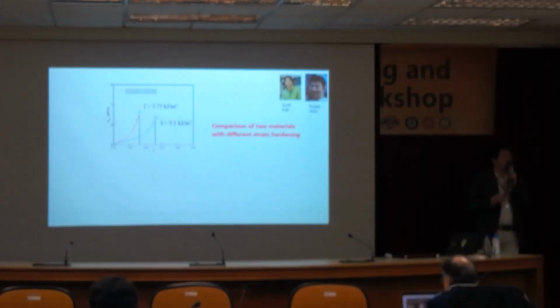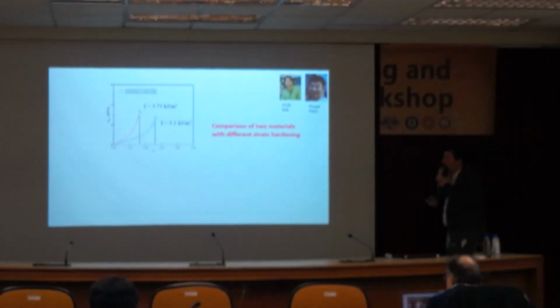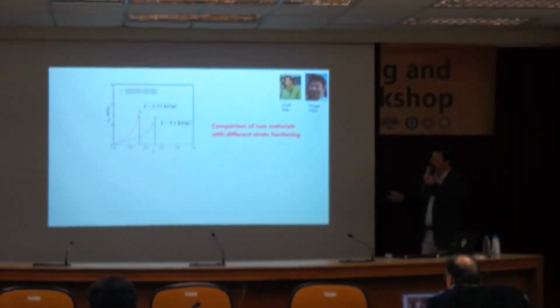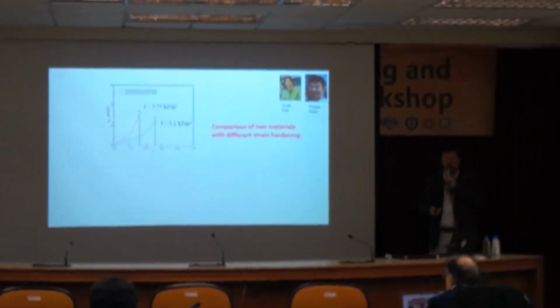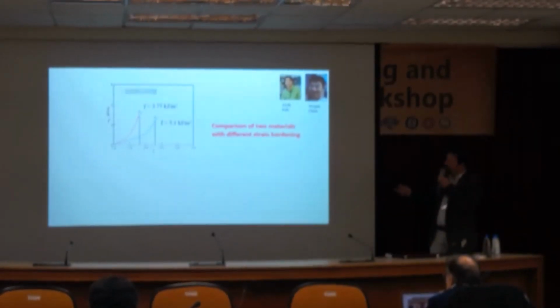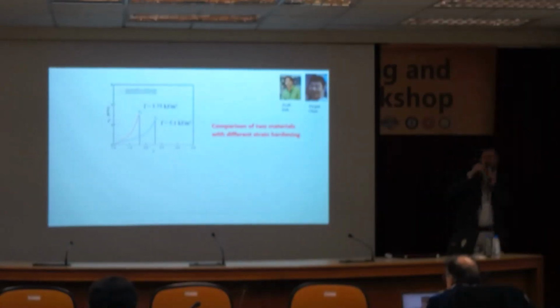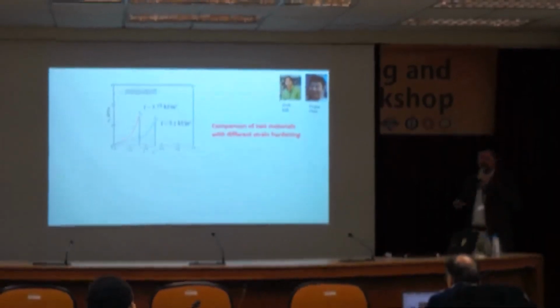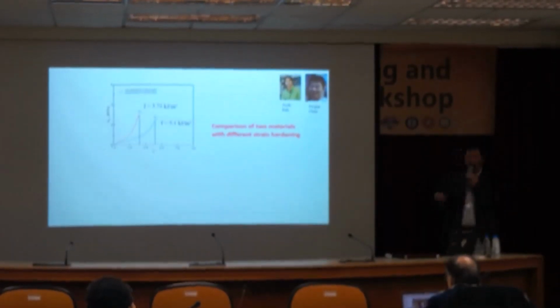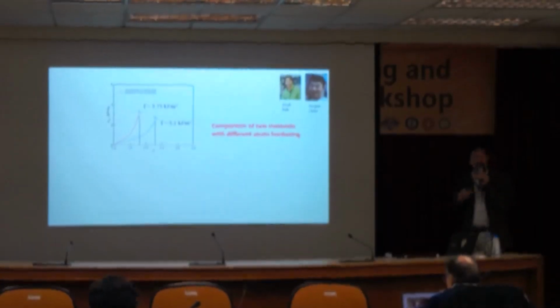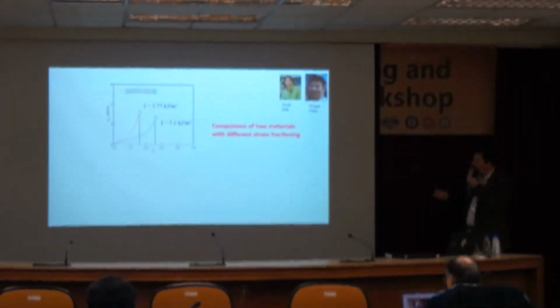So what can you do with it? One of the things you can do is mapping. Here we're looking at two different materials made with different properties, different fracture energies, and this is a stress strain curve with a notched sample. The sample has an initial crack, it's being stretched. If it was a linear elastic material, this would not be very interesting because we can predict everything with a simulation. But for these materials that are nonlinear, it's not quite as easy.